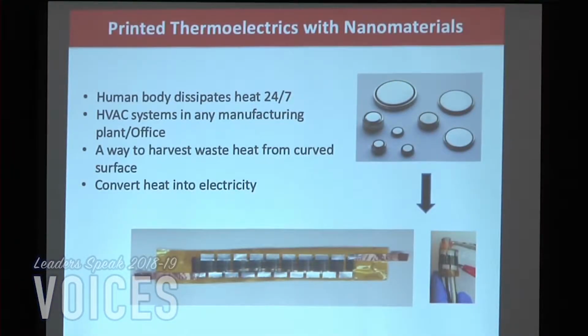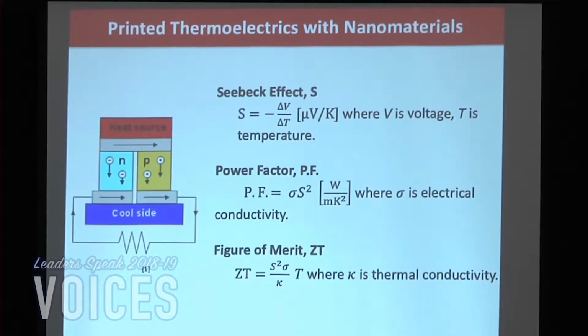And here's one of our samples, our first prototypes in the lab, where we're printing these black wires here. These are actually telluride-based nanowires. So bismuth telluride and lead telluride form the P and N junctions for this thermoelectric generator, and this is liquid metal that's been printed on top of it. And we can wrap this around a wire really tightly, and it doesn't crack, it doesn't break. We put a polymer on top of this so it doesn't oxidize either. So it works quite well.